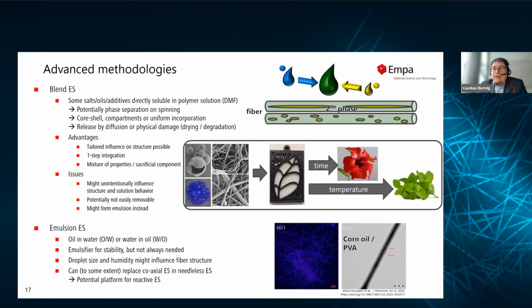So that's a bit of an academic problem. You can't 100% know what's going to happen. There will be some that actually stay in this sort of shape where you have these compartments inside. That would be ideal probably for drug release, as long as there is some sort of connection to the surface at some point. The other option is that you're getting a phase separation of some sort that might still be acceptable, but in the worst case, they are separating directly while spinning and you're simply getting 2 separate polymers. That can also happen. In this case, if you're lucky, you would have some sort of coating where the drug is incorporated to provide some extra stability. But in the end, you have to test it.